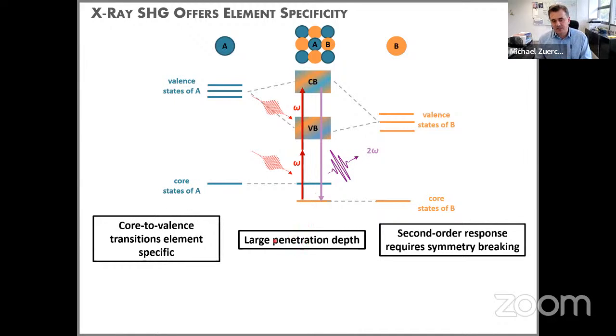The other thing that comes with using X-rays is that we have large penetration depth. We can typically shine X-rays through stacks of material. There is usually absorption, but depending on the photon energy range used, it can be quite low. That is quite different to, for instance, photoemission techniques that can probe surfaces, but only in very clean environments, basically an ultra high vacuum solid interface. Here, due to the large penetration depth, you actually get access to buried structures.